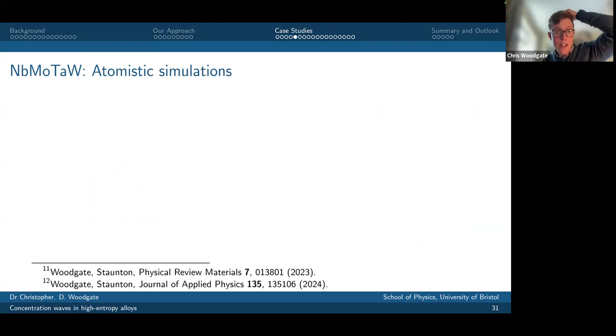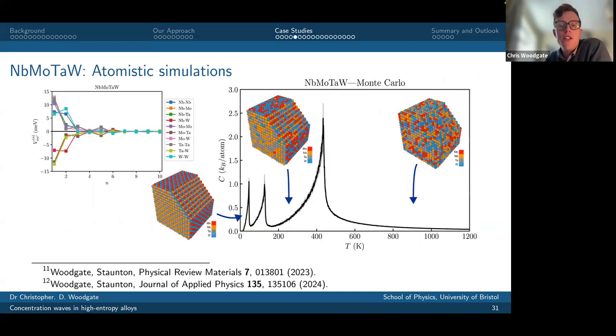I can use these effective pair interactions and do my Monte Carlo simulations. And so this is a plot purely of the configurational contribution to the specific heat of my simulation as a function of temperature. And what I see is that, at high temperatures, on the right, I have this disordered BCC solid solution. As I decrease the temperature, there's an initial peak in my heat capacity, and that's associated with the B2 ordering, so with niobium and tantalum moving to one sublattice, molybdenum and tungsten moving to the other.